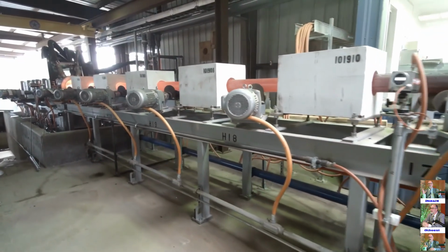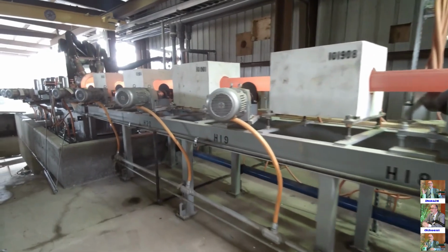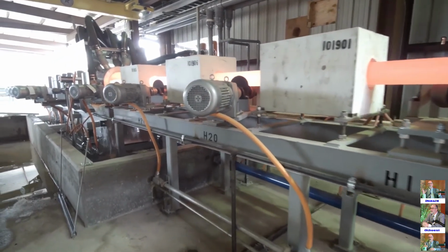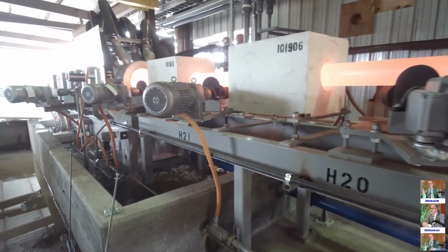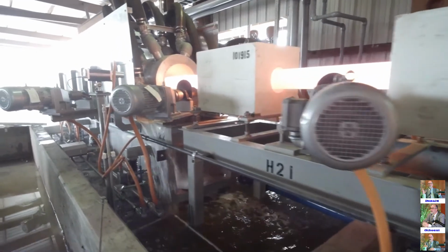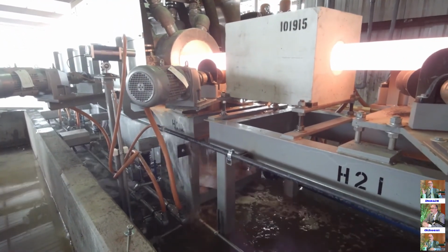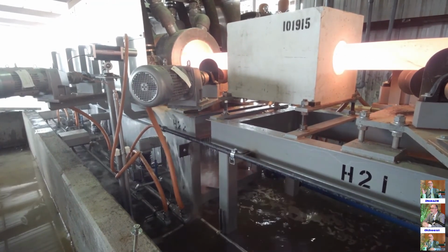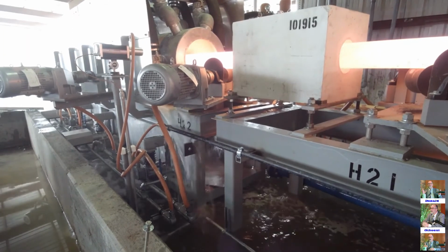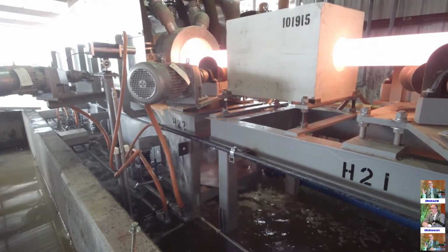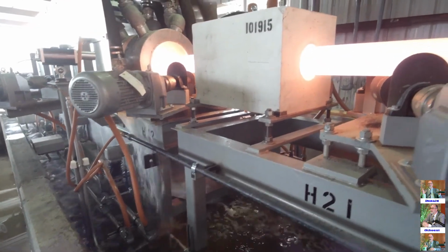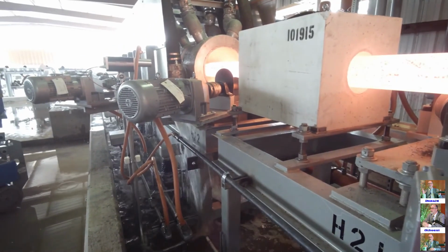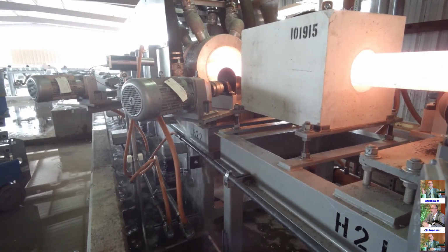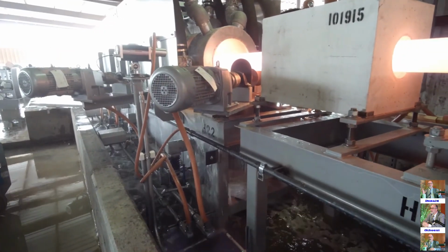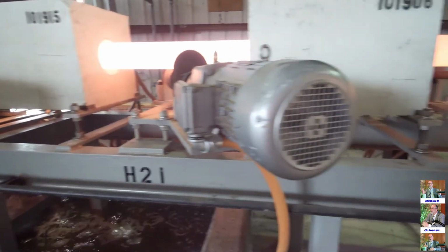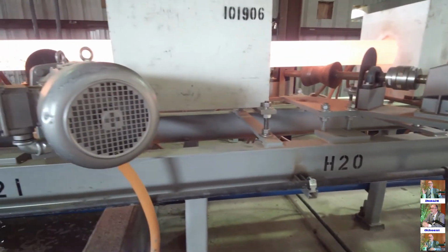There's an infrared coming off the first power supply that we can feed forward and adjust the second. And you can see the progressive heat here very nicely as it gets up to the end austenitizing temperature anywhere from 1650 to 1850. Here's that aggressive quench barrel system that we have. You see an infrared right there at the tail end. And you can notice there's not a lot of scale on this, even though the temperature is elevated above the scale formation point, which is typically around 1400 degrees. In comparison to a furnace, it's just much less. But the IR units have to have a decay rate, so that's more of a little averaging in case some of the scale does get picked up. The quench height is adjusted by those jack screws you saw on the bottom automatically through the controls.